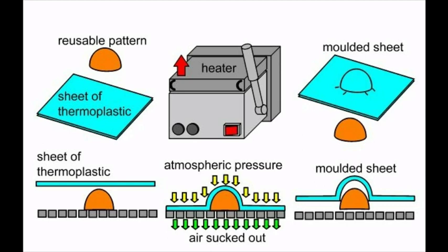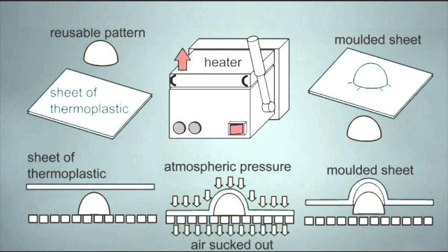Examples: polystyrene, acrylic, PVC, that is polyvinyl chloride, and polypropylene PP. All these are sheet materials with reasonable stability. Pre-stretch can be employed to give better distribution of material in the wall and to produce deeper forming. Example, the vacuum bubble snap-back technique.